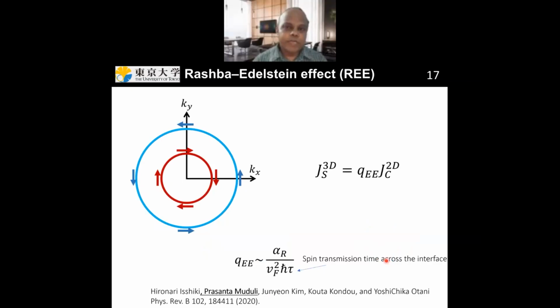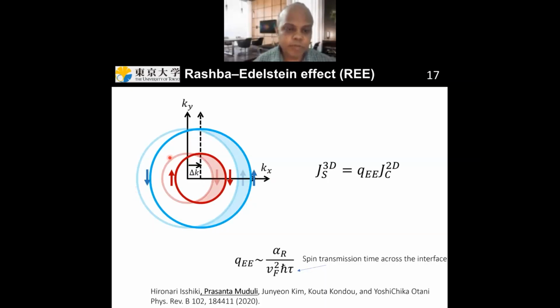So now let me show how you can convert spin current to charge current. As I said, we have two Fermi contours in a Rashba interface. Now if you pass a charge current, suppose along the negative x direction over here, then the Fermi contours will shift like this, and this will produce a net spin accumulation along the y direction. And if you now connect a metal close to this interface, then the spin current will be injected perpendicular to the surface, and you will create a 3D spin current.